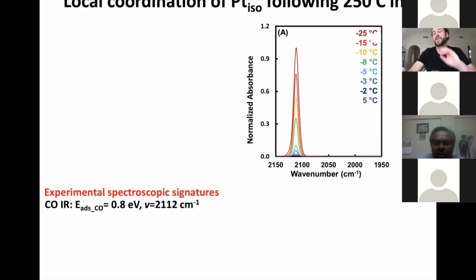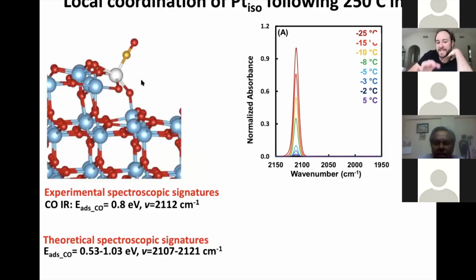So equipped with the idea that all of our spectroscopic characterization told us that we had uniform platinum species on a support, and they were likely all isolated, we then could say, okay, our vibrational frequency is about 2112. Redhead analysis tells us that our adsorption energy of CO is about 0.8 eV. And we can look through a library of different DFT calculations, and these were performed by Gianfranco Pacchioni, and look for different coordination environments that give us very similar behaviors. And so what we found is that PtO2 structures, both at a step edge and at a terrace, as I showed on the previous slide, give similar adsorption energies and similar vibrational frequencies. So far showing that we're on the right track in identifying our site.